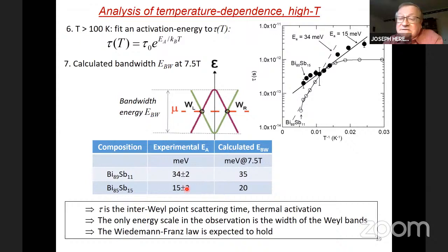So we think for the two concentrations, we have a very good correlation between the activation energy of the scattering time and the bandwidth. Meaning that essentially the bandwidth is what would determine the thermal activation of the scattering time. In other words, the way the system decays is by electrons being thermally excited from one Weyl point to another Weyl point and not mediated by phonons or such things. Which also means, of course, tau is the inter-Weyl point scattering time by thermal activation. And the only energy scale in the problem, which is this activation energy, is really the width of the Weyl bands, the bandwidth here.